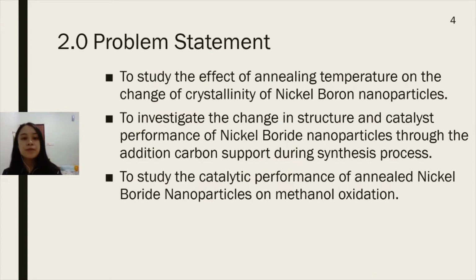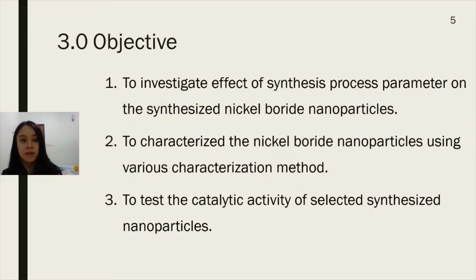My problem statement for this project is to study the effect of annealing temperature on the change of crystallinity of nickel boride nanoparticles, and to investigate the change in structure and catalyst performance of nickel boride nanoparticles through the addition of carbon support during the synthesis process, and also to study the catalytic performance of annealed nickel boride nanoparticles on methanol oxidation.